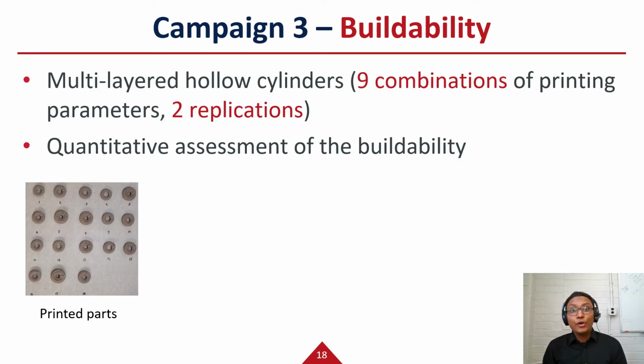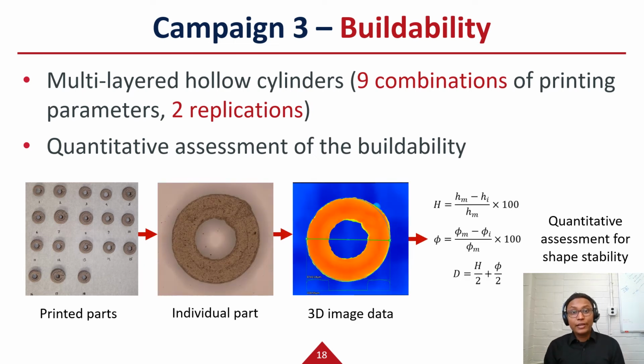In campaign 3, we considered 3 levels for both printing speed and extrusion rate. Speed was 12, 16, and 20 mm per second, and the extrusion multiplier was 1, 1.5, and 2. For a full factorial design with 2 replications, we printed 18 parts in total. Our goal here is to assess the shape stability of the material.